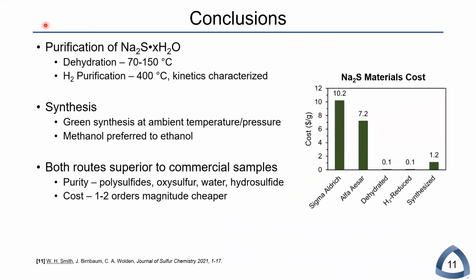So in conclusion, today I've presented on 2 routes to producing high purity battery grade sodium sulfide. The first being the purification of low cost technical grade sodium sulfide hydrate by first dehydrating the material and then reacting with hydrogen at 400 degrees in order to remove oxysulfur and polysulfide species, with the kinetics of this reaction being characterized for the first time. We also presented on the novel synthesis of anhydrous sodium sulfide in an alcohol solution at ambient temperature and pressure, with methanol being preferred to ethanol.